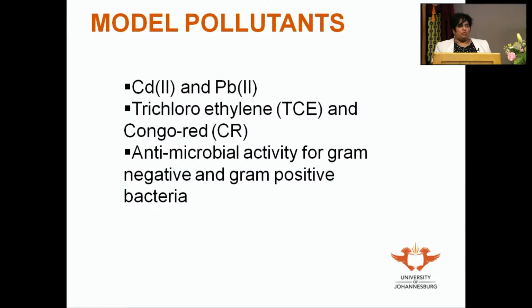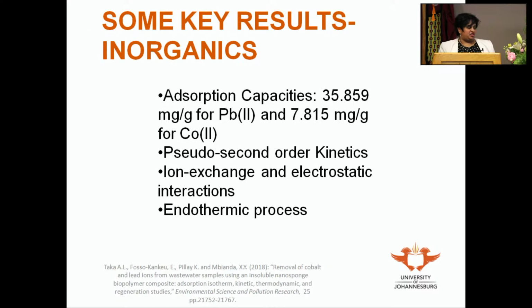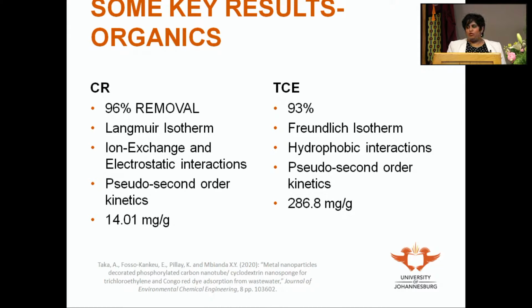So the model inorganic pollutants that we worked with were cadmium-2 and lead-2. The model organic pollutants were trichloroethylene and Congo red dye, and we tested the antimicrobial activity on gram-positive and gram-negative bacteria. This is to show you some of the results with the inorganics. You can see that the adsorption capacities were not very high, but there was some adsorption observed via ion exchange and electrostatic mechanisms. For the organics, we saw a good percentage removal above 90%.